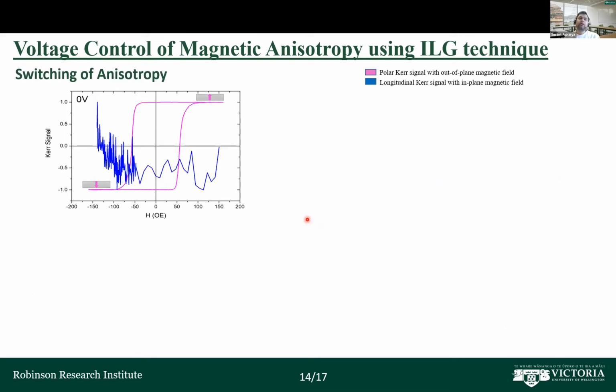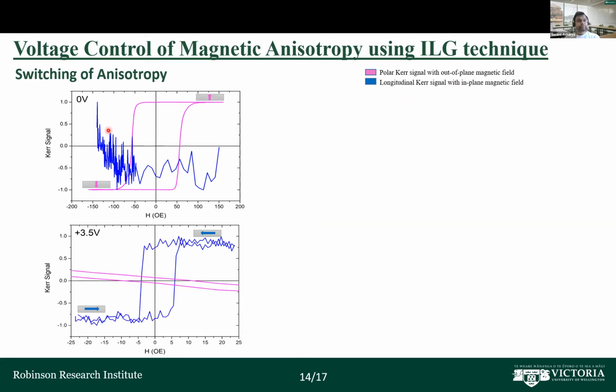To change the anisotropy completely, we have to apply a higher voltage. So to do that, you can see that this is at 0 volt. The polar Kerr signal is represented by the pink line, and the longitudinal Kerr signal is represented by the blue line. So clearly the anisotropy is out of plane direction at 0 volt.